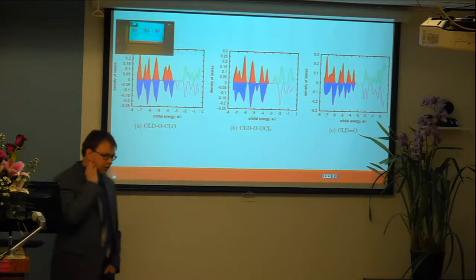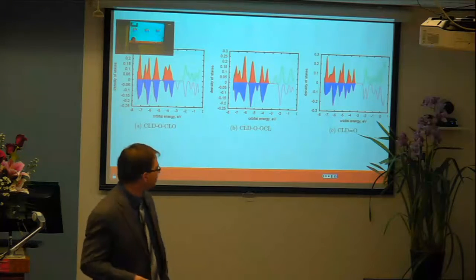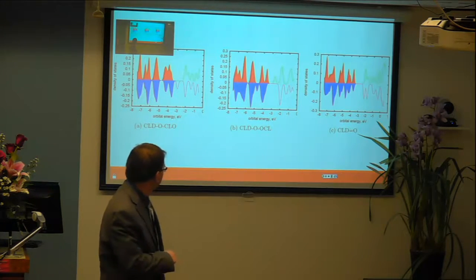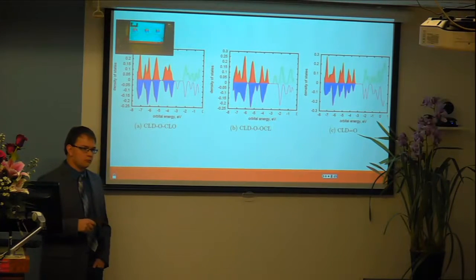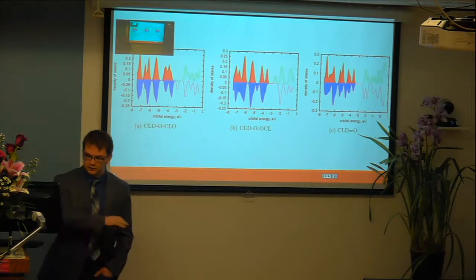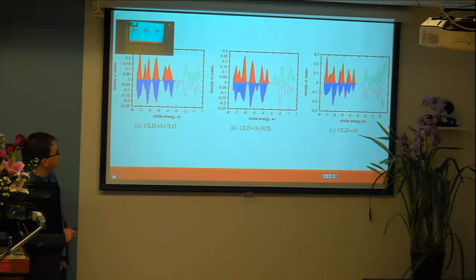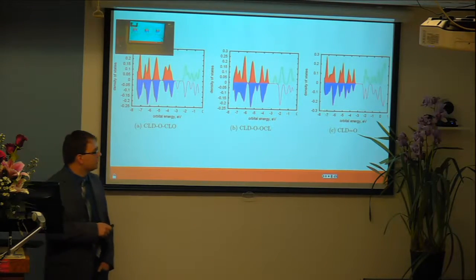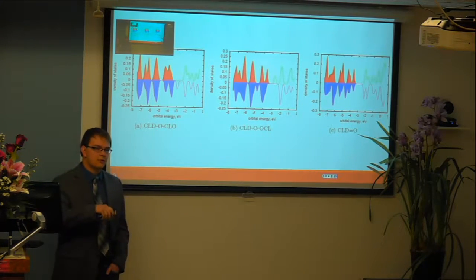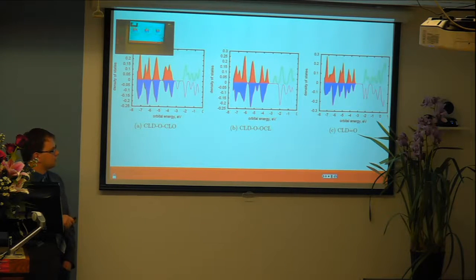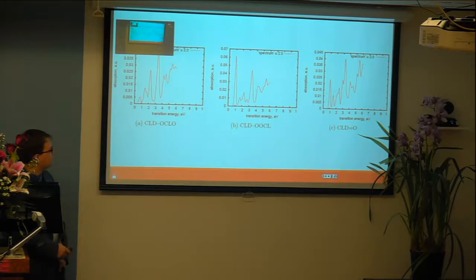Now we can look at the combined structure. Like I said, there are reaction pathways that are hypothesized and some seen in experiments. On the left, we just have an oxygen binding the hypochlorite and the iron, and that's shown here. Then the next stage, which has been seen in experiments, is a peroxide linkage, shown here, and another state as well. This is maybe the hypothesized transition state. The hypochlorite may be sitting above this macrocycle, stabilized maybe by a nearby charged arginine amino acid, and the absorption spectrum as well.